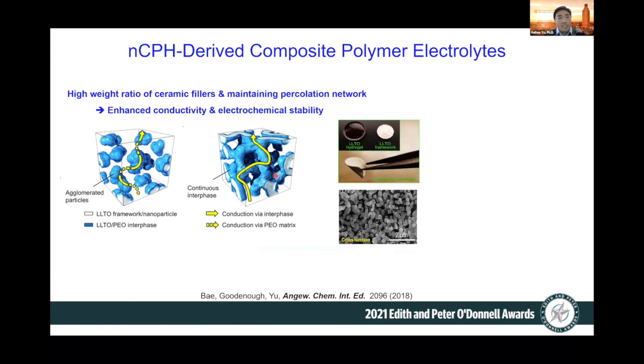So you can mix this ceramic precursor with the polymer precursor, and instead of the nanoparticle random network you have right now, you can form this pre-percolated network. So you can have a higher ionic conductivity and a better electrochemical stability.